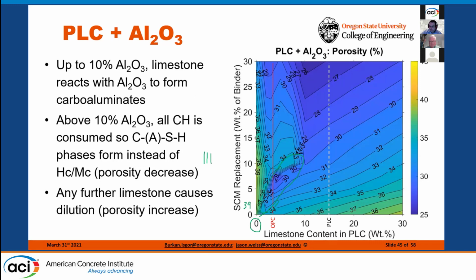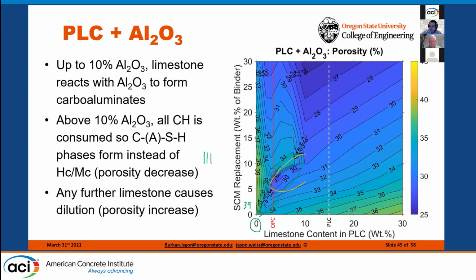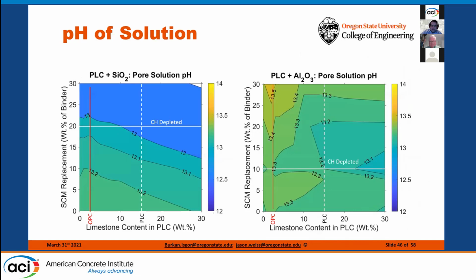And I've, of course, chosen the incredibly wrong color. So let me change the ink color here. And you get a very, very low porosity in these ranges here, right? You're seeing a huge benefit of that alumina reaction in the system, all right? This is going to be very beneficial when we talk about what happens when you add metakaolins, when you add slags, when you add any alumina-bearing phases into the system. As mentioned, we can also do other sorts of calculations.